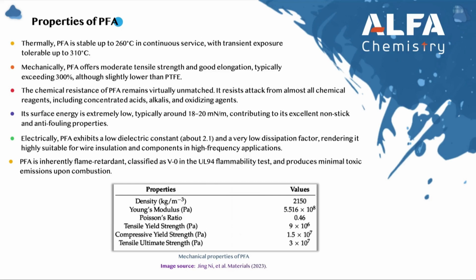The chemical resistance of PFA remains virtually unmatched. It resists attack from almost all chemical reagents, including concentrated acids, alkalis, and oxidizing agents. Its surface energy is extremely low, typically around 18-20 mN/m, contributing to its excellent non-stick and anti-fouling properties. Electrically, PFA exhibits a low dielectric constant, about 2.1, and a very low dissipation factor, rendering it highly suitable for wire insulation and components in high-frequency applications. Moreover, PFA is inherently flame retardant, classified as V0 in the UL 94 flammability test, and produces minimal toxic emissions upon combustion.